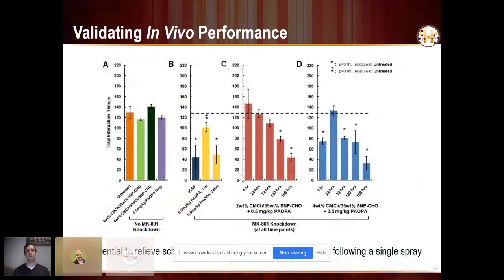What we saw experimentally is if we don't treat these animals for the 5-minute time we view these in the arena, we call it. Sounds like a fight, but it's really not. For 2 of the 5 minutes or so, this is measured by a blinded observer, the rats were judged to be in active interactions. If we deliver our vehicle alone without drug, or the drug alone without the knockdown, without inducing the schizophrenia symptoms, we see the exact same interaction time. Once we induce the symptoms, though, if we just treat with artificial cerebral spinal fluid, we see about 1/3 of that interaction time now. So the huge change in the amount of time the rats are actually interacting with each other.